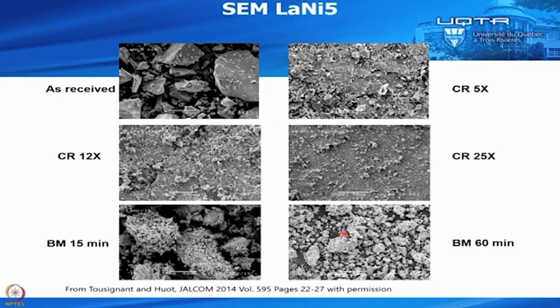So this is a morphology. The as received one is like big block. So this is 50 micron. So this is almost 100 micron. So you have big particle. And when you cold roll, basically what you do, you take all these particles and you make a small plate with it. Okay. So you see that.